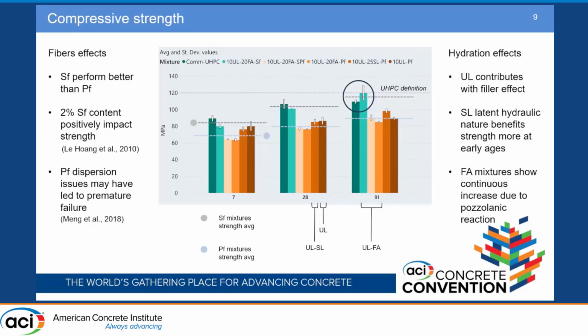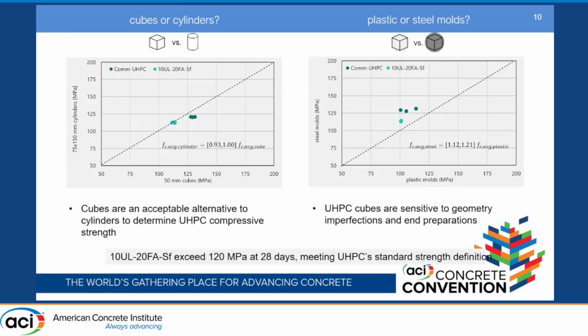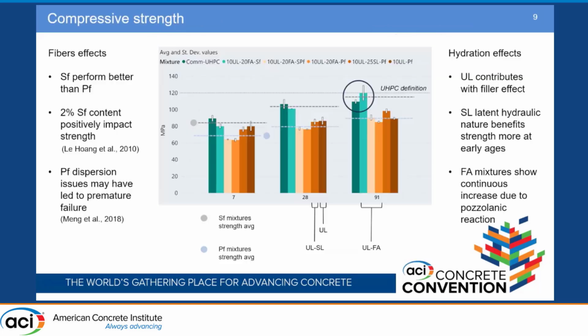Also, we could see that the different SCMs help in the strength development. The limestone with a filler effect, and the slag at early ages, while the fly ash contributes more at later ages. So at 91 days, one of our mixtures overperformed the commercial UHPC and met the 120 megapascal strength requirement that most of the used UHPC definitions require.